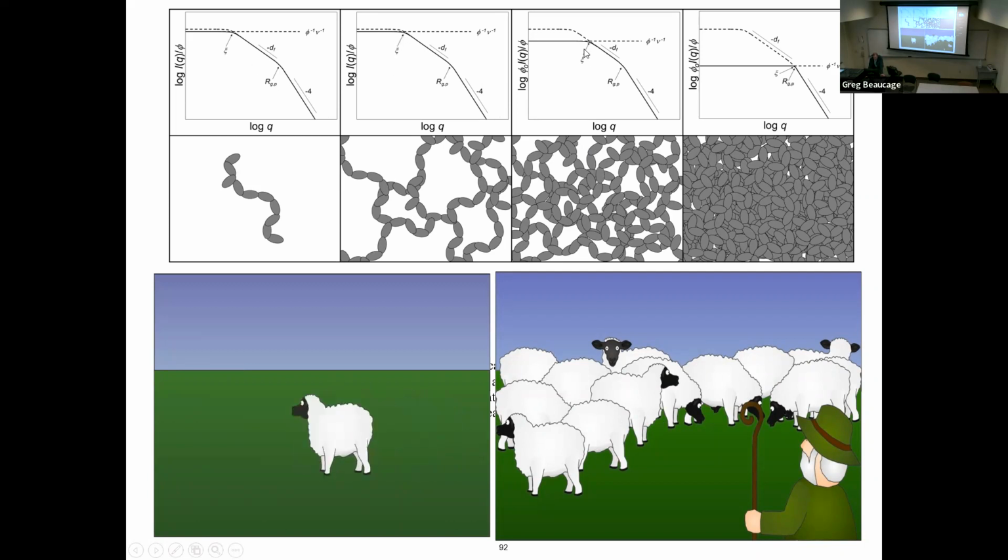So basically the size scale that comes out here is like this network. How big is the network? What's the distance between chains, the mesh size of the network, basically, right? And as you get to higher concentration, the mesh size is smaller. This is 1 over size, so it kicks out to the right, right? And then below that, you see just uniform. So below that size, you see uniform.